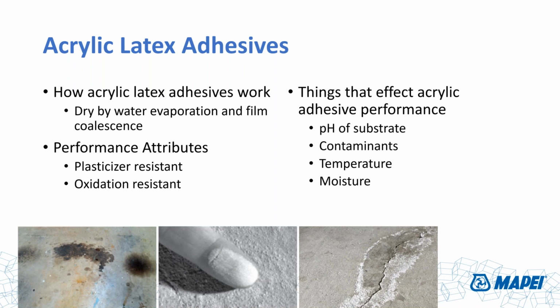So if you're dealing with a concrete slab that's 15 pounds moisture vapor emission, 99% RH, and you're installing a high performance moisture resistant PSA adhesive, but don't let it dry out completely and stick LVT on top of it or sheet vinyl on top of it, you will have a problem. It's very important to make sure that it's all very dry. Again, the performance attributes: they're plasticizer migration resistant, oxidation resistant, but they still have many of the same sensitivities that SBRs do.